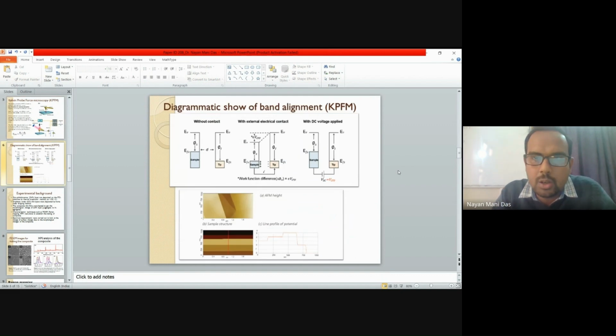So this is the schematic of the KPFM. This is the metal tip, which has a work function of phi t, and this is the work function of the semiconducting sample. If they come in contact, there is a band alignment going on, so there is the appearance of this contact potential difference. If we give some potential from the outside, this potential will compensate this VCPD, the contact potential difference, and from that the instrument calculates the change in the voltage occurring over your surface.